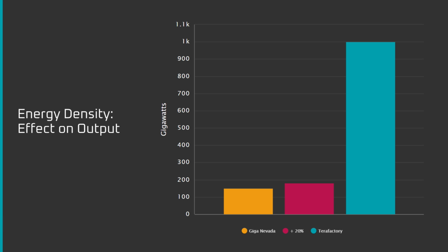A 20% specific energy improvement is a conservative expectation. However, even a 30 to 40% specific energy density improvement is a drop in the bucket compared to the hundreds of percent improvement needed for a Terafactory. We'll stick with 20% to be conservative.